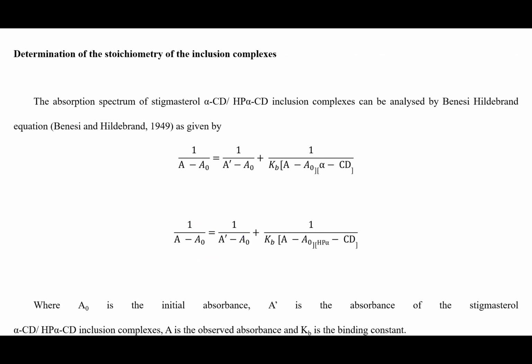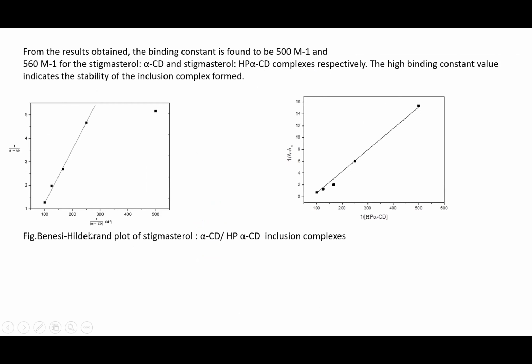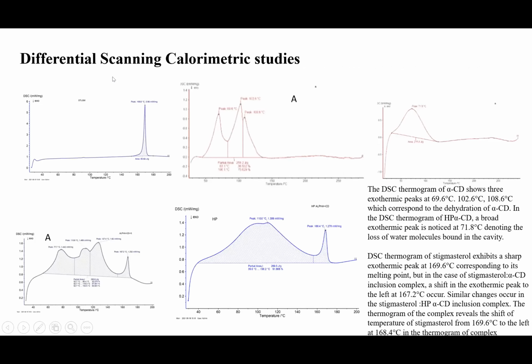So using the Hildebrand equation, I have plotted a graph to calculate the binding constant of both complexes. This is the equation used. And here is the plot of 1 by concentration of alpha CD versus 1 by A minus A naught. A straight line is obtained. From the slope, we calculate the binding constant value, and the binding constant here is 560 for HP alpha CD, and it is a little lesser for the alpha CD complex.